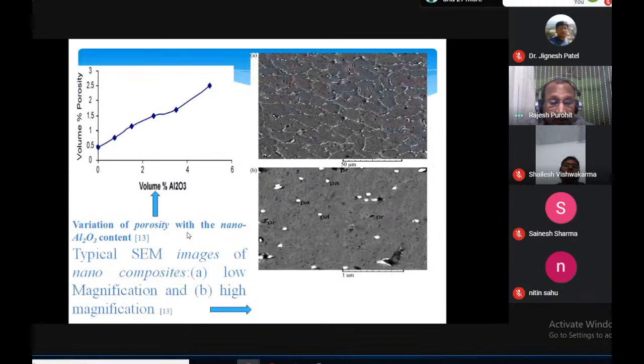Now this is showing variation. The first graph shows the variation of porosity with the nano-sized aluminum oxide content. We see that with increasing volume percent of aluminum oxide, the porosity level is continuously increasing. What happens is that the particles become points of porosity, and more porosity is assembled near the particles. Because of that, at higher weight percent or volume percent, the porosity level is increasing.